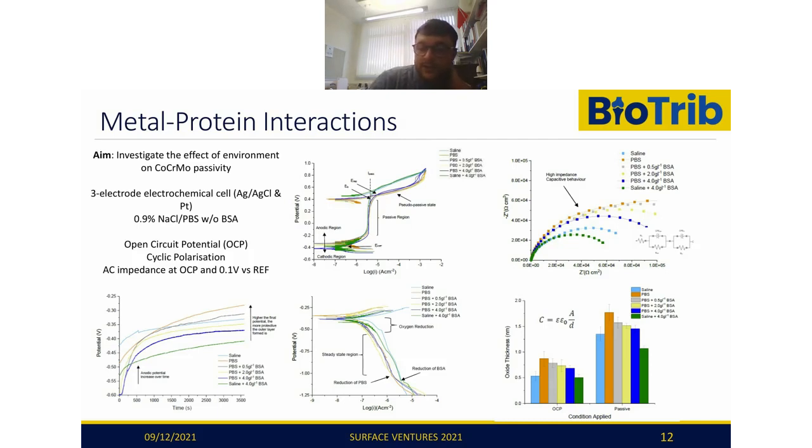And in general, the phosphates tended to reduce this corrosion current and these passive currents, but they also tended to reduce what we would call the breakdown potential. So it gave an indication that whilst the phosphates decreased the overall static dissolution, the susceptibility of these films to breakdown and to loss due to corrosion was increased with the presence of phosphates.